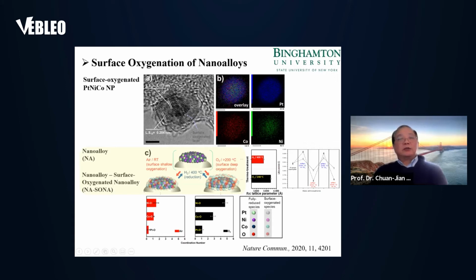One of the ways to do that is to introduce temperature control and different concentrations of oxygen. So we can call it shallow oxygenation, as illustrated on the left-hand side, or deep oxygenation, as illustrated on the right-hand side. We can actually confirm this using an X-ray diffraction study, as illustrated in the far right panel. When we reduce them using hydrogen, we have lattice shrinking. When we oxygenate, we can see lattice expansion. So we can do this lattice shrinking and lattice expansion reversibly. This process is reversible. We can do this all the time.